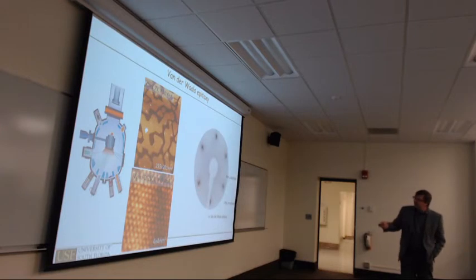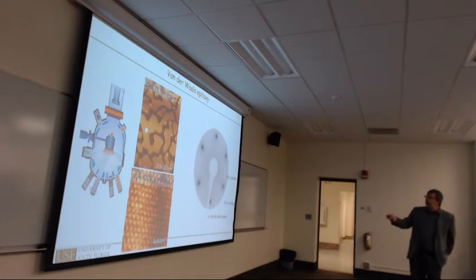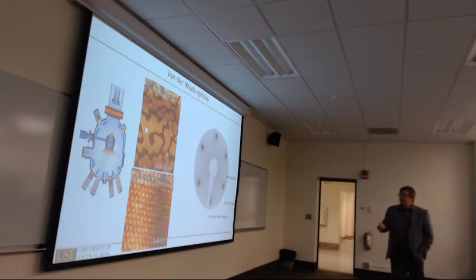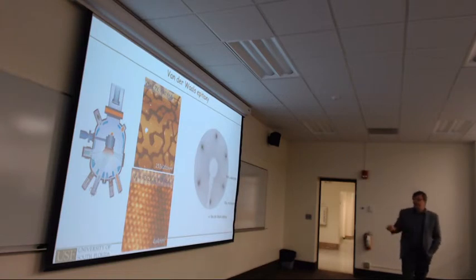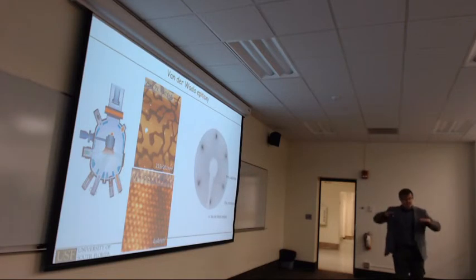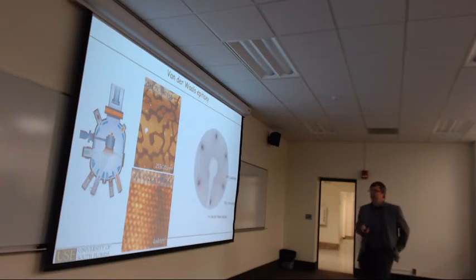It's hard to resolve here, but here you see two little spots. One, the outer one, is from the molybdenum sulfide substrate, the substrate with the smaller lattice constant. And then you have another spot here, which is vanadium selenide, which has a larger lattice constant, so it's more to the center of the reciprocal space. But the important part is that the spots are aligned in the same rotational direction, which means that the film we grow is in the same orientation as the substrate, and that's what we call van der Waals epitaxy. So the film and the substrate have independent lattice constants, so they're not stretched, they are rotationally aligned.